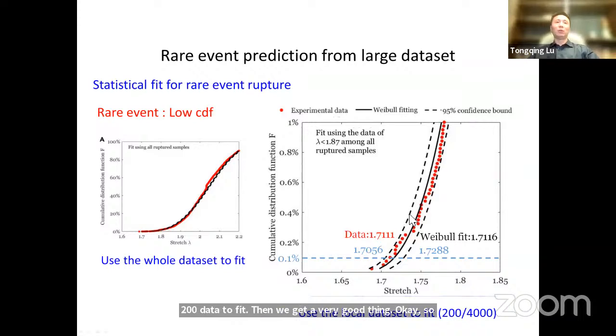We will not go into the details. In this figure, the red dots are experimental data. The solid line is our Weibull fitting, and the two dashed lines are the 95% confidence bound. Let's look at the rare event, for example, the blue line. This is a 0.1% rare event, which, because this is 4,000 samples, means the first 4 samples to have rupture. You can see all the experimental data falls within the 95% confidence bound, which means the Weibull prediction accurately predicts that this rare event happens between these two stretches. Very accurate prediction.